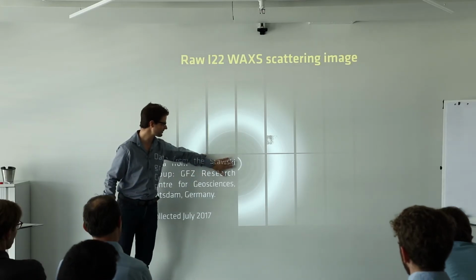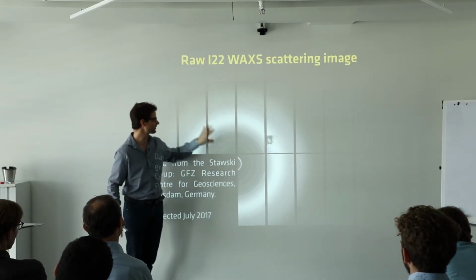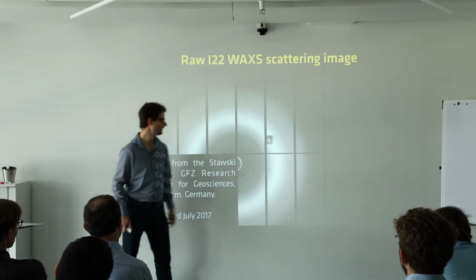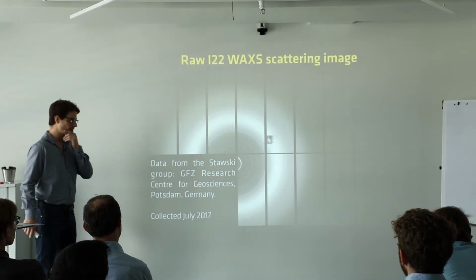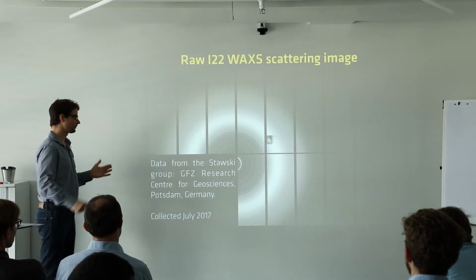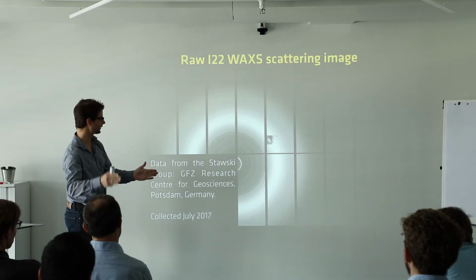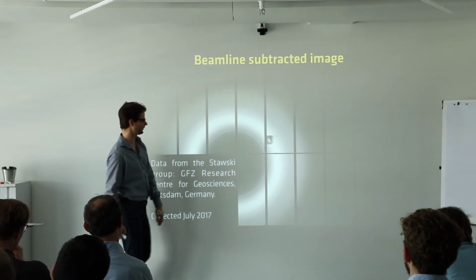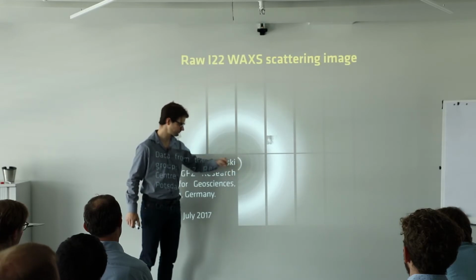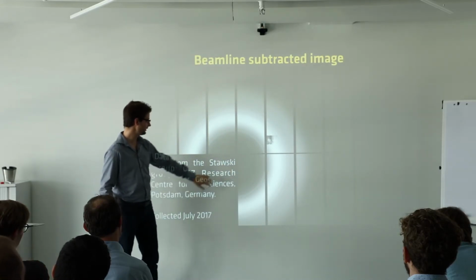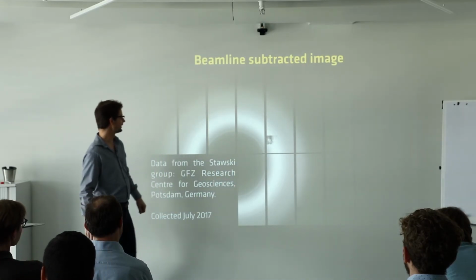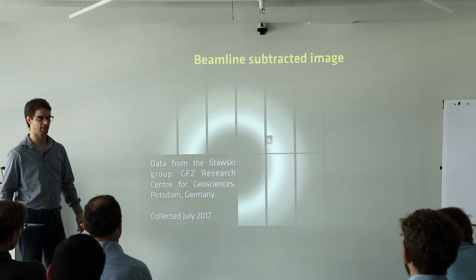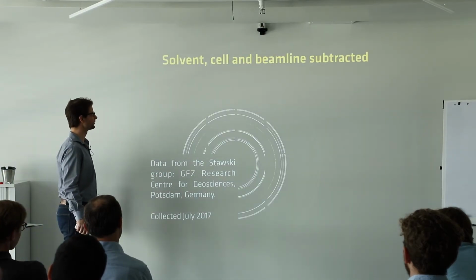So behind this sits the small angle scattering detector, and this is then the wide angle detector. They then subtract their beamline background, which includes two Kapton films and a bit of air scattering. And if you do that, you see that this one is missing. These are the Kapton peaks in the middle. And then you can subtract the cell and the solvent, and then you're left with this.